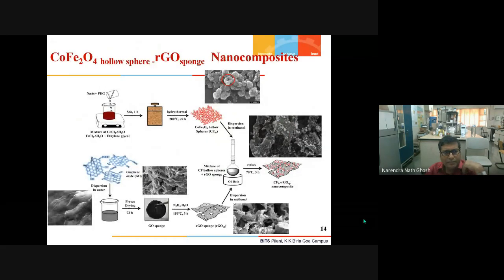Here is another one. It is an aerogel sponge composite, cobalt ferrite hollow sphere and rGO sponge. First of all, let me tell you that all these methods are not complicated at all. We have done everything on the open bench, and in some cases we have used a furnace. We did not use any glove box or any very elaborate reaction setup. In some cases, we need an oil bath or some reflux in the system, that's it.